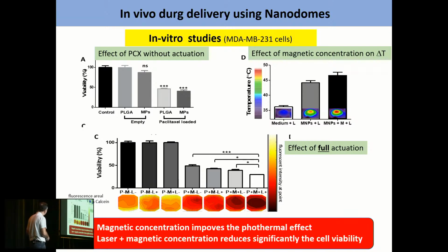And then we tried the optical heating, and you see here that when we use the laser without magnetic concentration, we can reach an increase of temperature of about 20 degrees. But when we do magnetic concentration, the temperature increases even further, because now, as I showed you in the in vitro experiments, we concentrate the nanoparticles in the optical path, and that makes them more efficient.